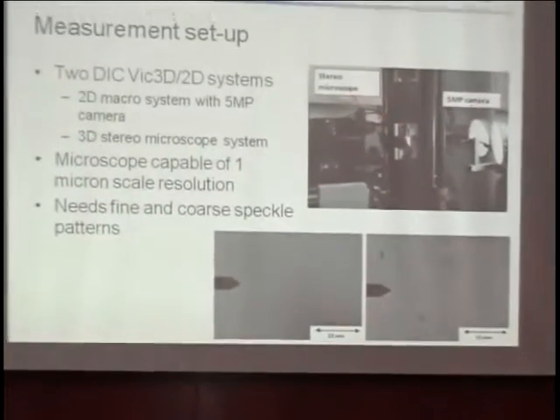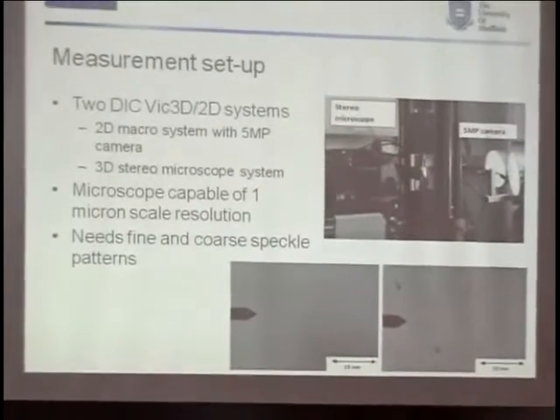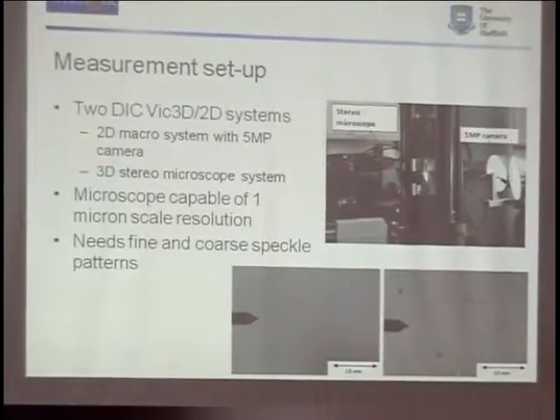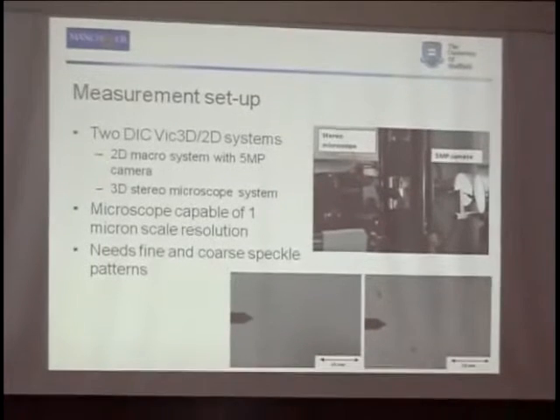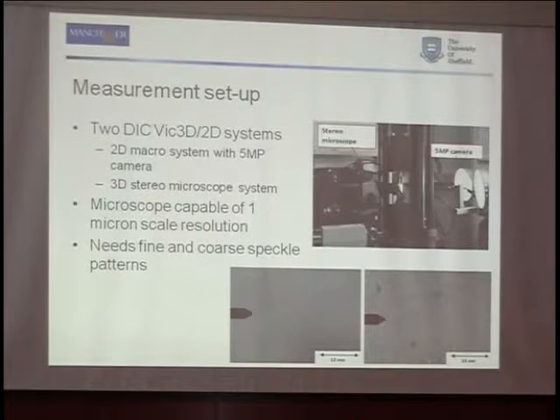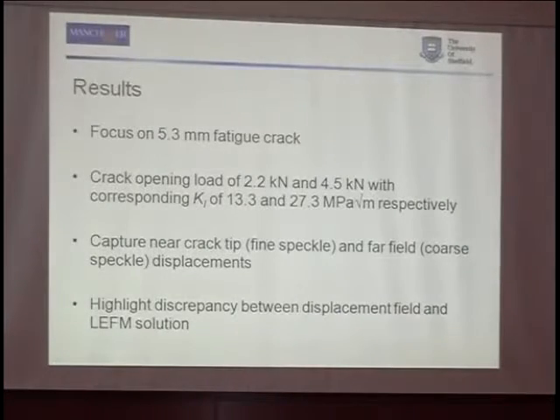So we did the test, cycled the specimen, and at different crack lengths we took a series of images. We had to slow it down because the cameras were not high-speed cameras, so we had to slow the test down to get a sequence of images. I could show you a couple of videos of the macro, but let's just go to the results.